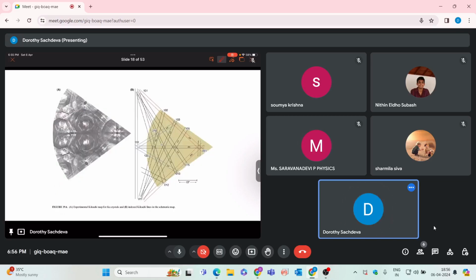So this is again the Kikuchi line map for your FCC crystals. For your FCC crystals also you will have the 001 zone axis and you can follow any of the roads to go to some other zone axis. But remember that there is a certain limitation in your instrument. If your pole pieces are very close, you have to put your specimen inside the instrument like this, and if the distance between the pole pieces is very small, then there is some restriction on tilting of your specimen. So you need to keep this in mind. There is one alpha tilt and there is one beta tilt.